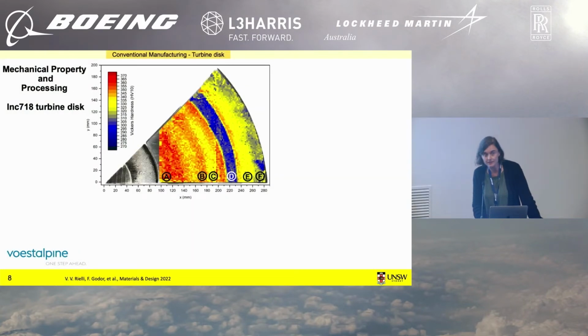So what you can see here is the slice of a real-world forged turbine disk made out of Inconel 718, and it's overlaid by a hardness map. You can see there's vast differences because these parts are actually really complicated, and what we don't want to have, so this is kind of a worst-case scenario map here, in this blue region D, we achieve a way lower hardness than in the other regions.